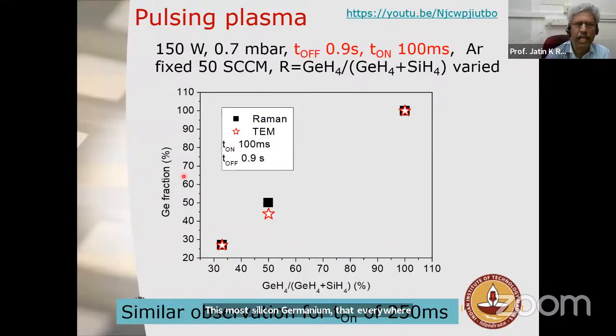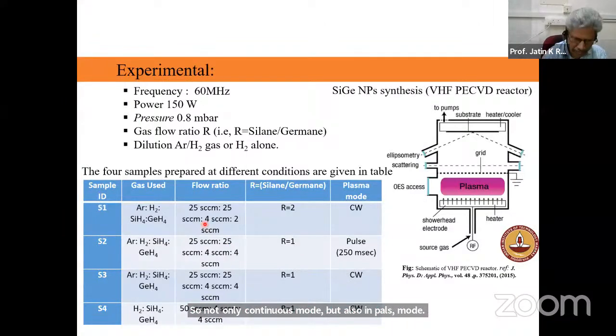So the germanium fraction, if you do pulsed plasma also, similarly, we could change the concentration of germanium in the quantum dots gradually by changing the germane to silane ratio. So not only in continuous mode, but also in pulsed mode, we can vary the germanium to silicon concentration nicely.